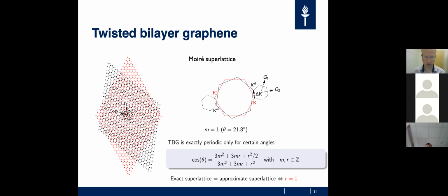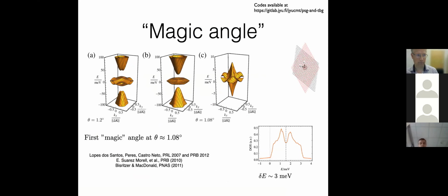In fact, bilayer graphene is exactly periodic only for certain commensurate angles, but they become dense at small angles. So we only concentrate on those commensurate angles. You can study the normal state spectrum as a function of the twisting, and you find out that there is this so-called magic angle at 1.08 degrees where the bandwidth becomes smallest. It's still finite, but it's quite small compared to the bandwidth before. One model that you can do with tight binding presents basically around 3 milli electron volt bandwidth for the region which has a large density of states.